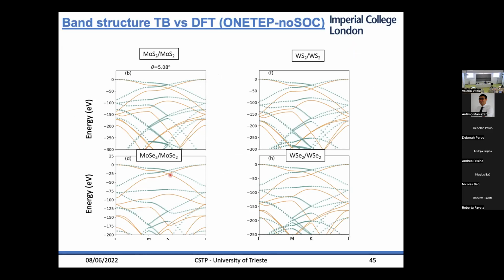So basically these are valence band structures of different transition metal chalcogenide twisted bilayers at 5 degrees. Green is tight binding and orange is DFT. And as you can see, the description is not perfect, especially the bandwidth is quite off, but you get all the symmetries of the bands right. You can improve the description, as we have done later in a different work, by going to 4th, 5th, and 6th neighbors, and there the agreement becomes much better.